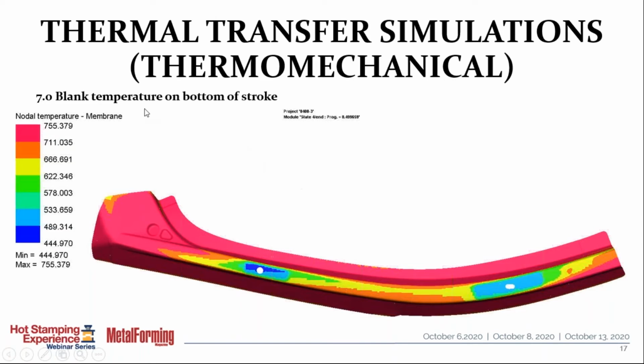In this case, what we're doing is at the moment we reach bottom of stroke, we'd like to know what the blank temperature is to make sure that it's above 400 C, which is where we start seeing very rapid transitions from austenite into martensite. So to the extent that we can keep the temperature up during forming, that's great. We want to make sure that we're fully formed before we start getting cold spots that start getting hard, like these points here. The reason these are getting hard is in this particular tool, we had pressure pads or force pads in these areas over the locator pins to help those pins hold the material in position. And so that started quenching out the material before the forming was accomplished.